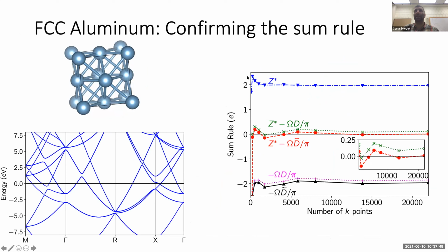So here I'm plotting, the units of the y-axis are electrons, and the units of the x-axis is the number of k points we use to integrate over the Brillouin zone. So just a convergence parameter. And we can see that the Born effective charge in aluminum definitely doesn't vanish. In fact, it converges to a result around 2 electrons.